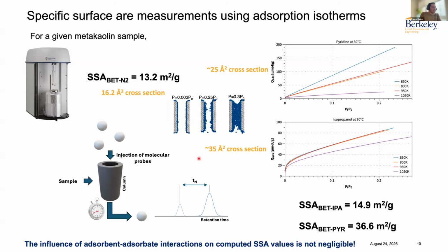I added these molecular cross sections here because what many people assume is that the reason why these surface areas change in values is because the molecules are larger or smaller, so they start occupying more or less space over the surface. But actually you can see that it doesn't follow the trend, because pyridine is actually larger in cross section than nitrogen, and still we measure a higher surface area. So it's really a chemical interactivity process going on here rather than geometrical space occupancy.